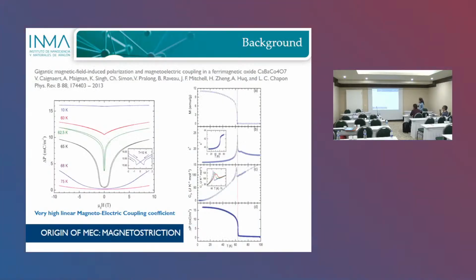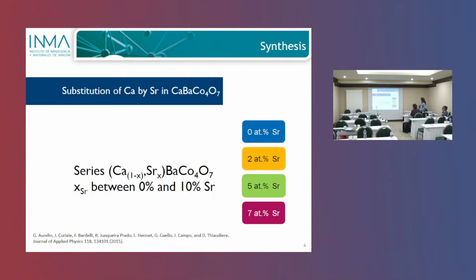So this compound is not strictly, you don't have a reversibility of the polarization signal, but what you have below 60 Kelvin is an increase in polarization, which is triggered by the magnetic transition, as you can see here, because as you apply the magnetic field, you can see how this change in polarization achieves a value at low temperature that is indeed very high for pure multiferroics. So the origin of this magnetoelectric coupling is supposed to be in a magnetostriction mechanism, and I am signaling here the value of this jump.